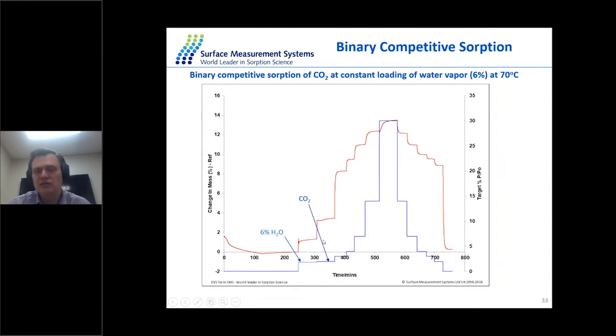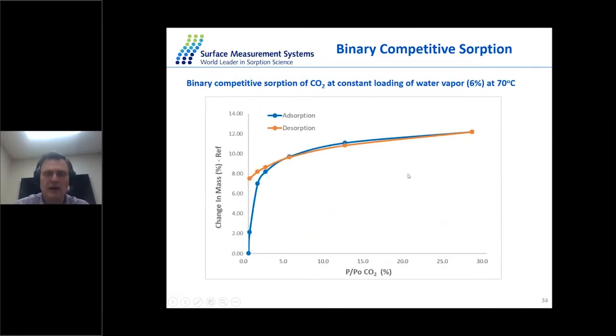As we introduce pressure, in order to raise the pressure we need to introduce a second species, and we use CO2. So we introduce a small amount of CO2 and wait for the mass equilibrium. But we assume that the CO2 is not replacing the water molecules. As we do this and go up to 30%, we can obtain the adsorption capacity of this material in the presence of water at 70 degrees. If I subtract my initial water uptake from the subsequent water plus CO2 uptake, I get my adsorption curve, where I can see that at 70 degrees, at a constant loading of water vapor, in this case 6% RH, I get about 10% uptake of CO2.